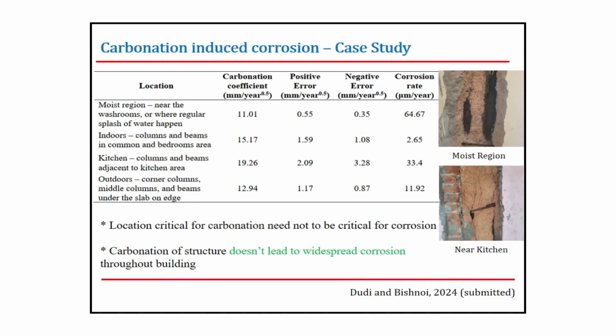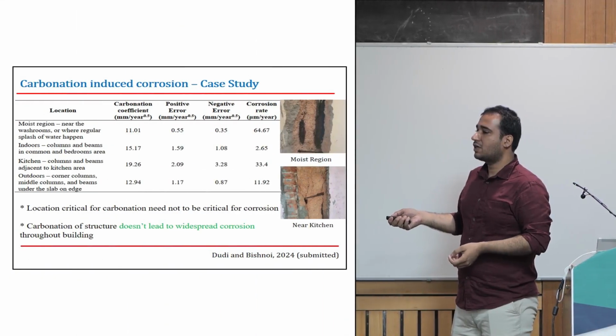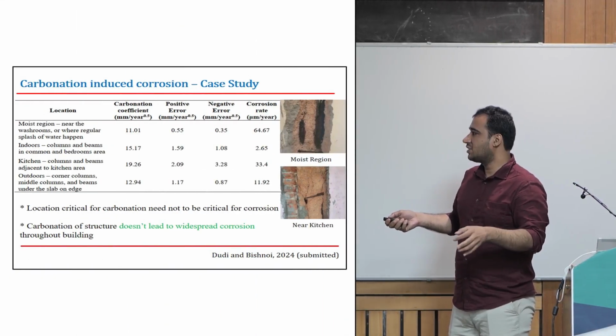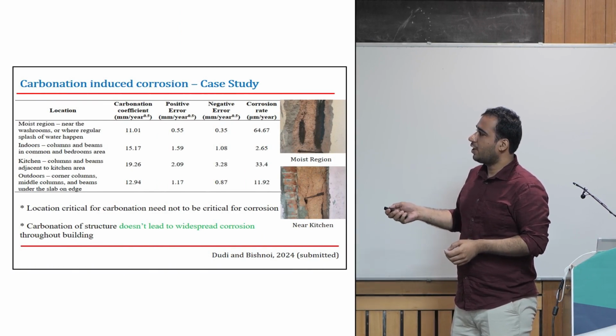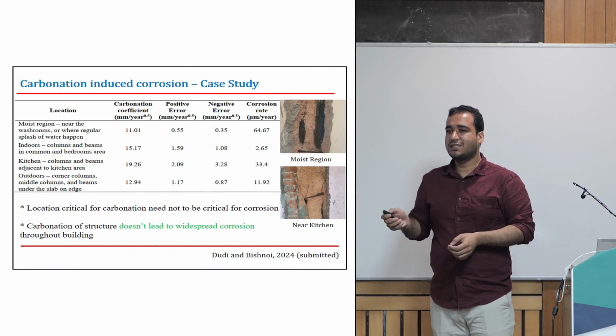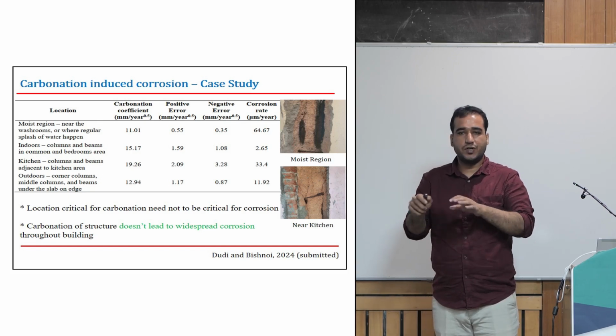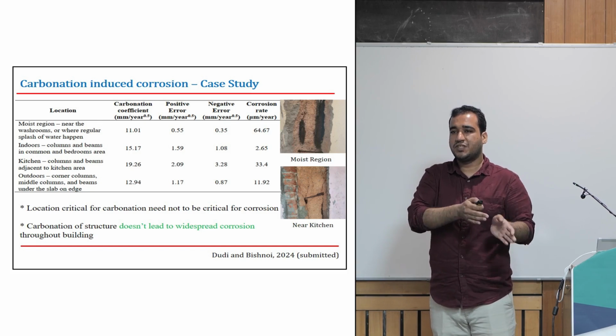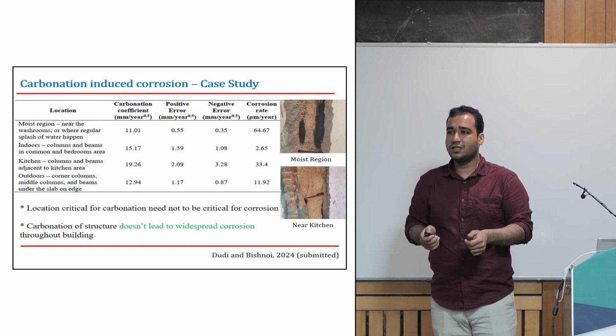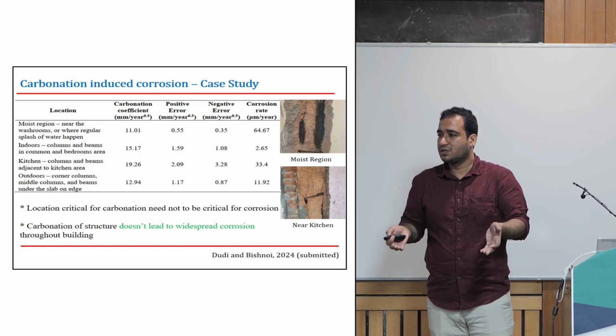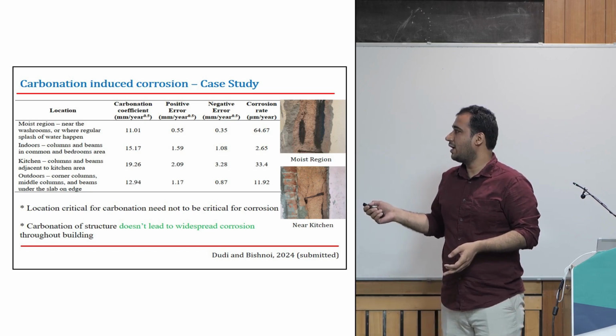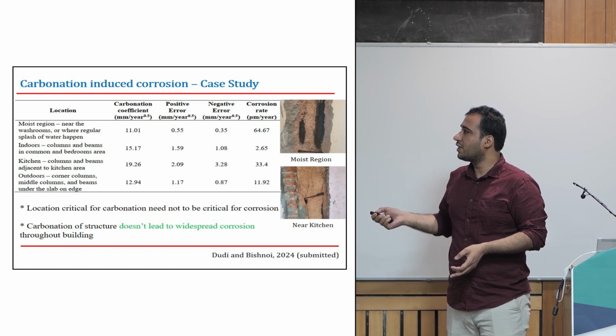This is a study we did on a half-century-old structure that was still serviceable up to last year. Now we demolished it because we need more space and more flats in IIT Delhi. So what we did is we determined the carbonation depth for different members in the structure, and we see that the values were quite high. Looking at these values, I can say that within the first 10 to 20 years, the depassivation of the rebar has occurred. But for the last 30 years, the structure had still been used for service. Only certain regions had high corrosion rate. The rest of them were quite low.